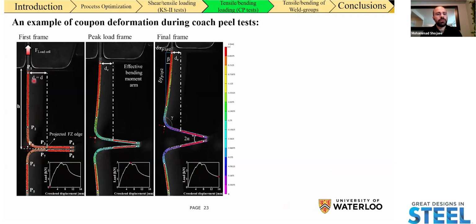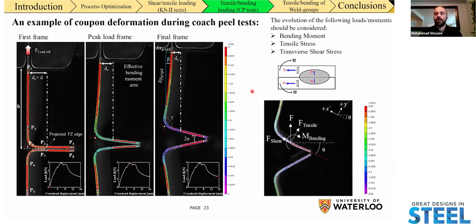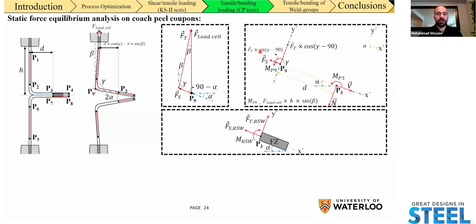You can see how the initial arm, this D term here, is essentially reducing throughout the whole test, and the angles, which I refer to as 2 alpha, beta, and lambda or gamma, are evolving. The evolution of all these moments and loads can be tracked if we perform an equilibrium analysis on the coach peel specimen. Since our tests are all performed at quasi-static strain rates, equilibrium should hold throughout the whole test, which is why we performed a static force equilibrium analysis on the coach peel coupons.